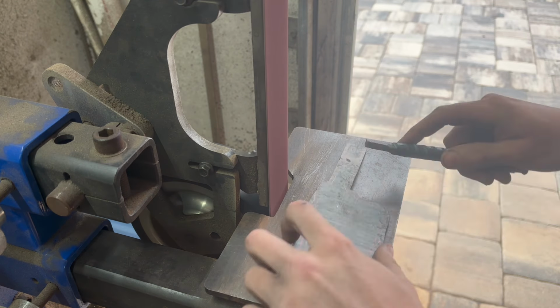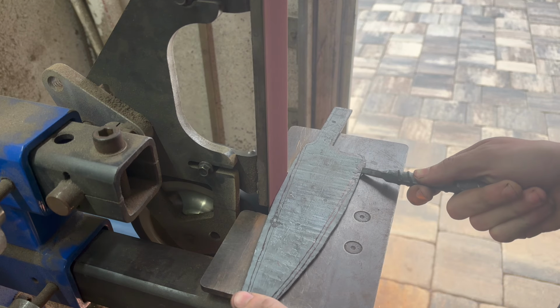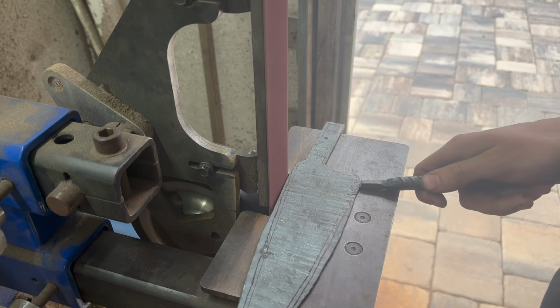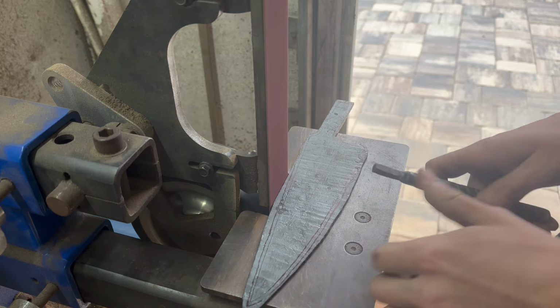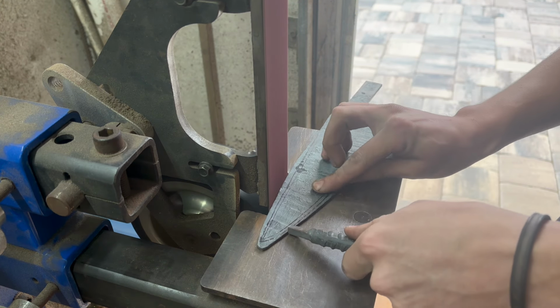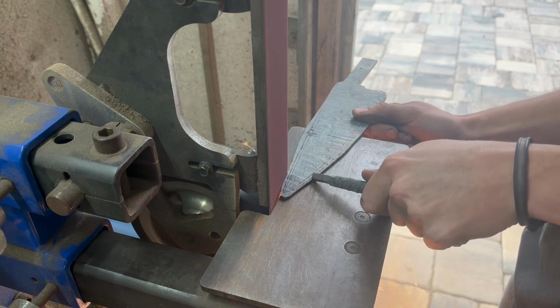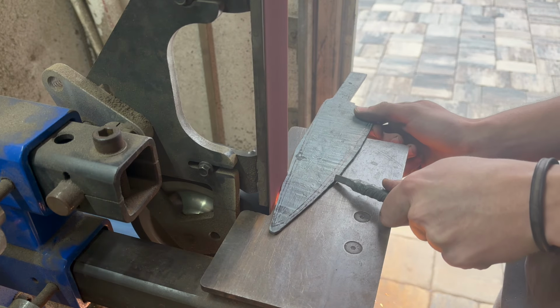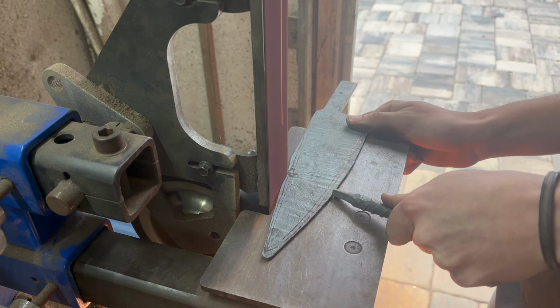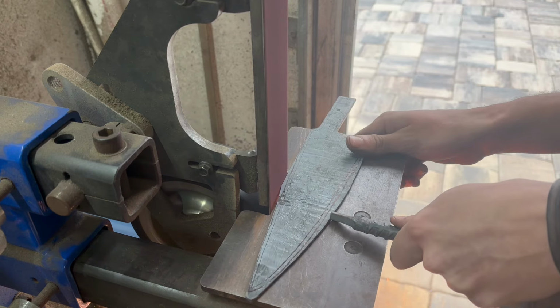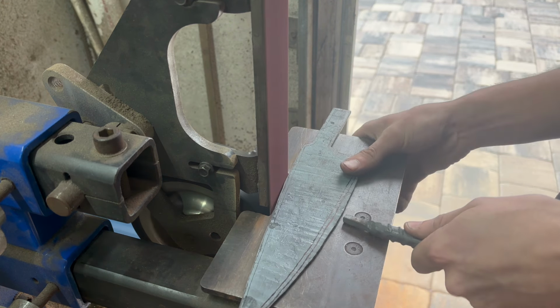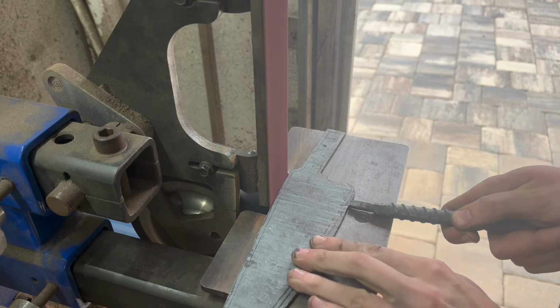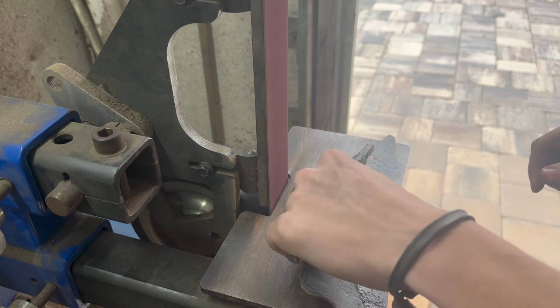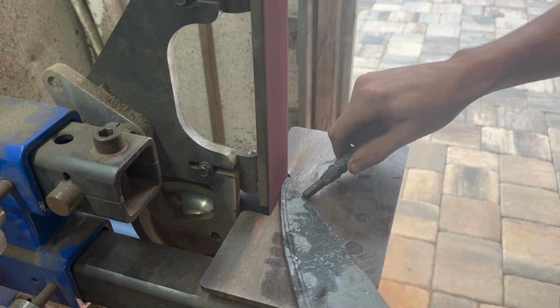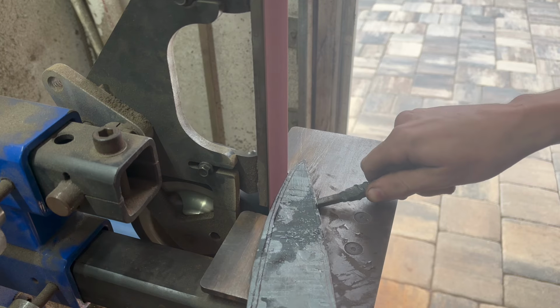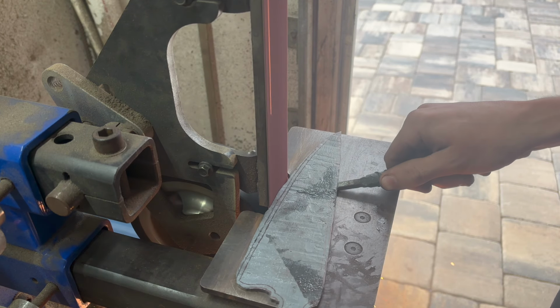Forging extremely even, because forging one side more than the other will cause that layer of steel to want to warp differently in the quench, which can cause the core to crack. And that's just another thing that can happen, is you have just the 3 layers that they can all want to do something different. You also just don't have as many chances of getting the weld set like you do with Damascus. Every time you're cutting and restacking the billet, you're strengthening all the previous forge welds, where with San Mai, you're kind of just doing that once, and it has to be perfect that first time.